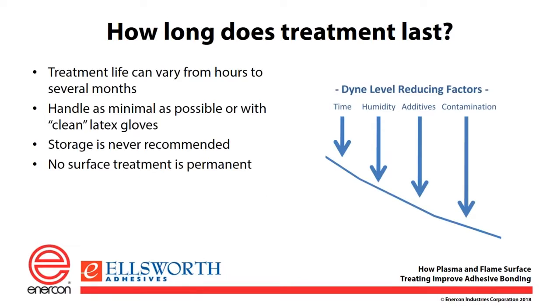How long does treatment last? This is one question that I get asked all the time, and the variables on the right that you see all affect the Dyne levels and make them go down. Each material has a different life. Basically, you'll treat something, you'll go from a low Dyne to a high Dyne. It'll have a steady state time, I call T, and that could be anywhere from a few seconds to a few days to a few months, depending on the material and then how it's stored. Then it's going to generally go back down.